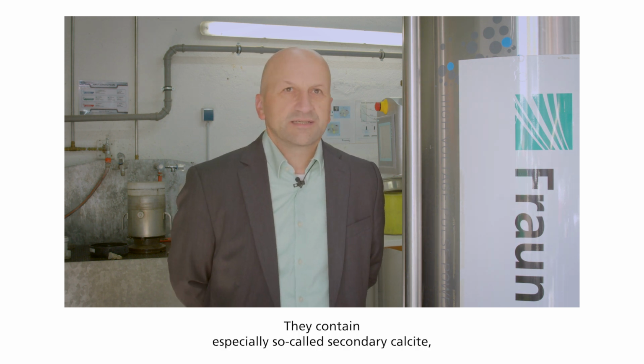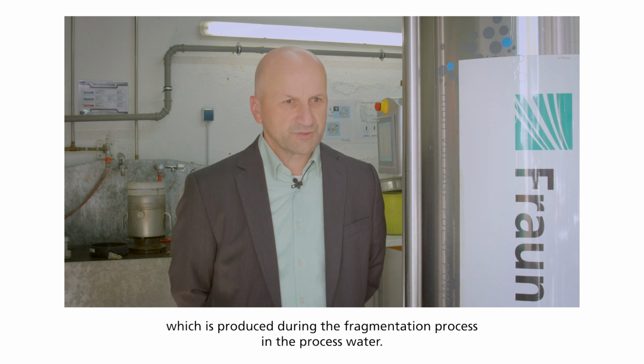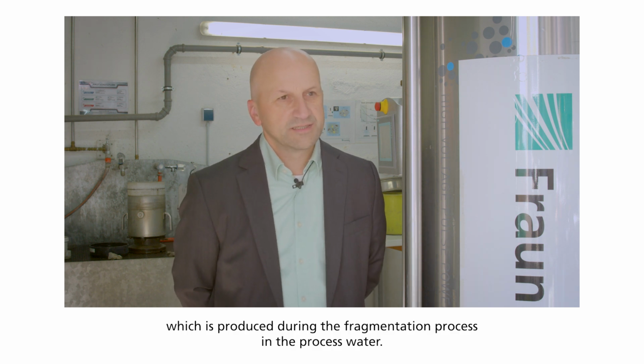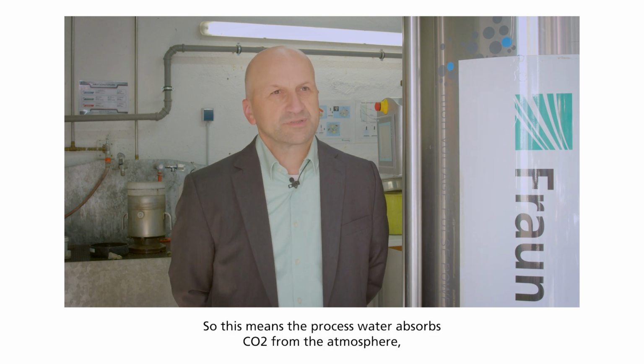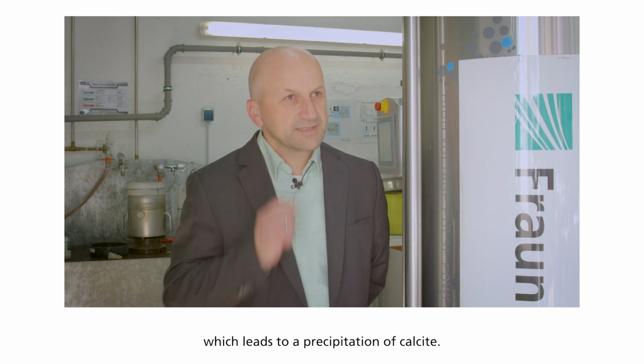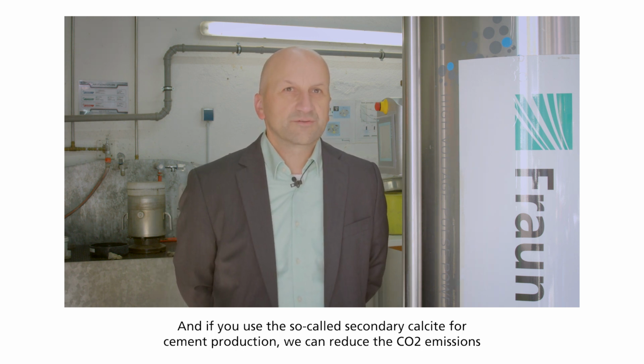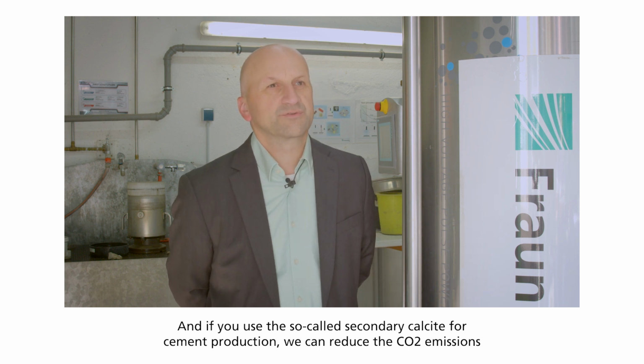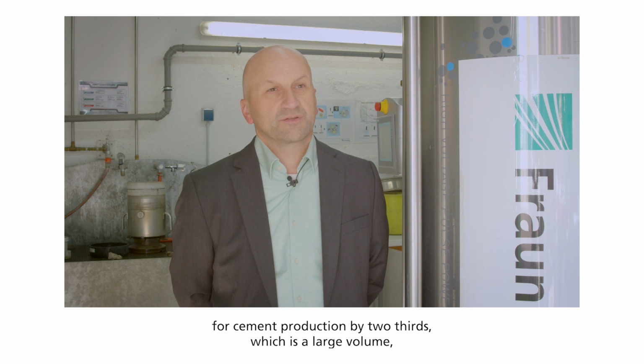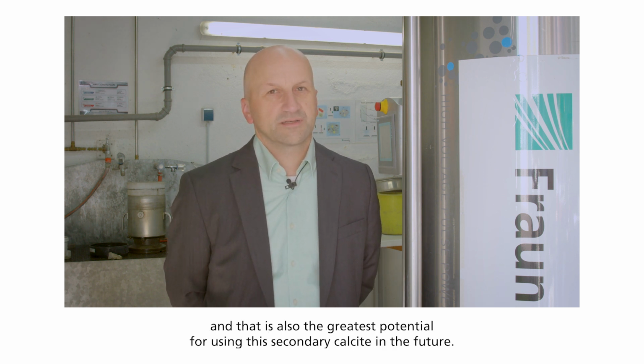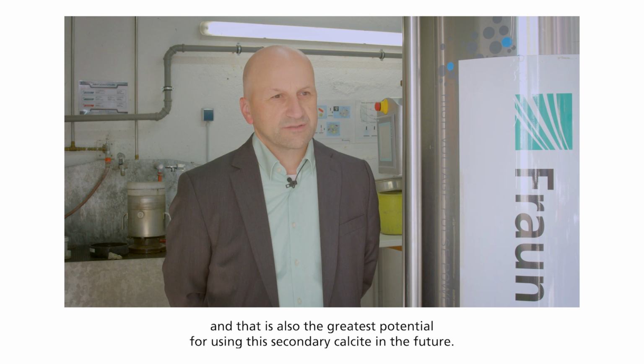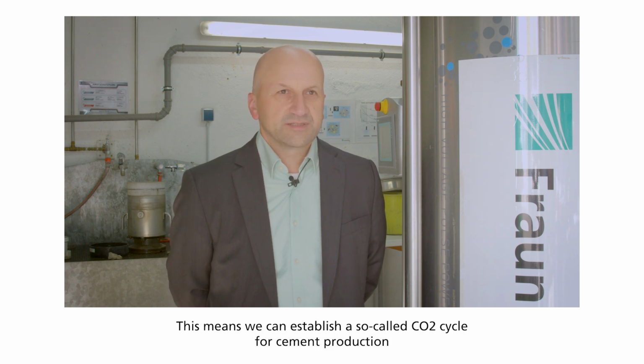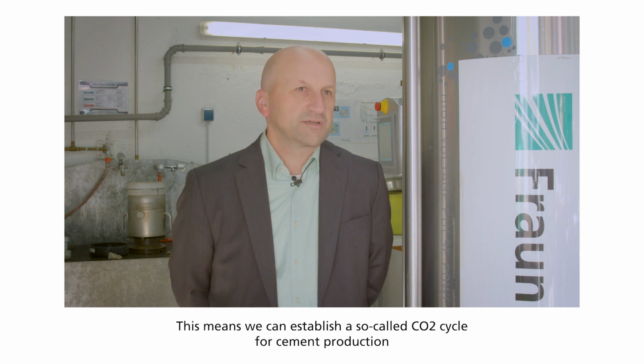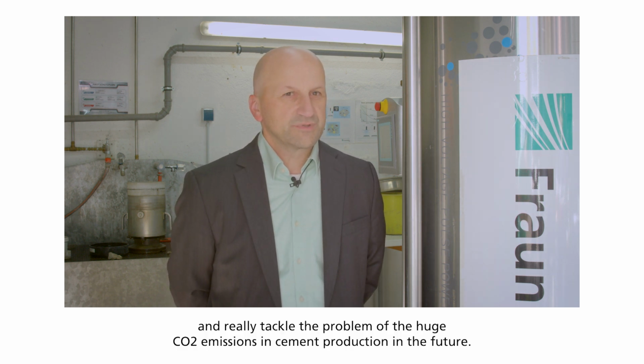They contain especially a so-called secondary calcite, which is produced during the fragmentation process in the process water. So this means the process water absorbs CO2 from the atmosphere, which leads to a precipitation of calcite. And if we use this so-called secondary calcite for cement production, we can reduce the CO2 emissions for cement production by 2/3, which is a large volume, and there's also the greatest potential for using this secondary calcite in the future. This means we can establish a so-called CO2 cycle for cement production and really tackle the problem of the huge CO2 emissions in cement production in the future.